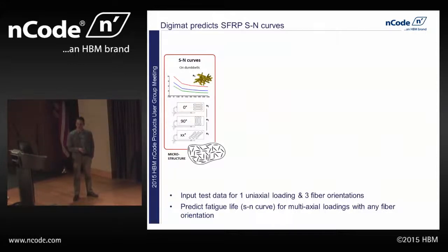But one of the really nice things about Digimat is that we're not just taking into account the mean direction of the fibers, we're taking into account how much randomness is in there and how that changes as you move through the thickness. So we're actually going to be looking at the actual fiber orientation in this part and representing that pretty accurately. So we're going to take these dumbbells that are cut from the plaque at these different orientations, and then we're going to test them, and we're going to end up with 3 SN curves that look something similar like this.